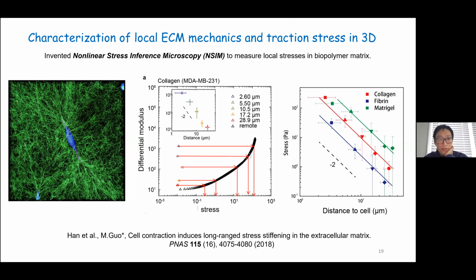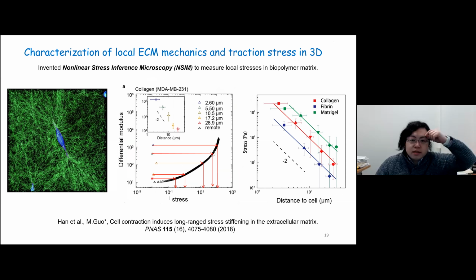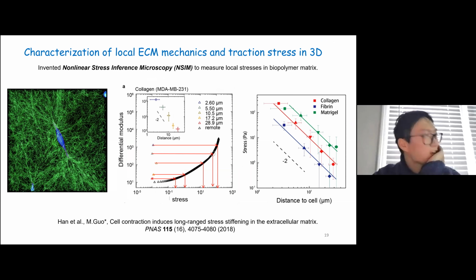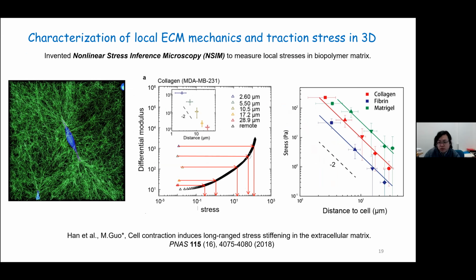All right, any questions about this part? Yeah, Ming, I have a question here. You show this for this material, which is basically strain stiffening. Does this also apply to strain softening or even yielding material, where you have a curve that goes downwards? First, I think yielding likely will not work because it's not monotonic anymore. Softening, I think so. I don't see why not. Yielding, most of it has to be reversible. It has to be elastic, actually.